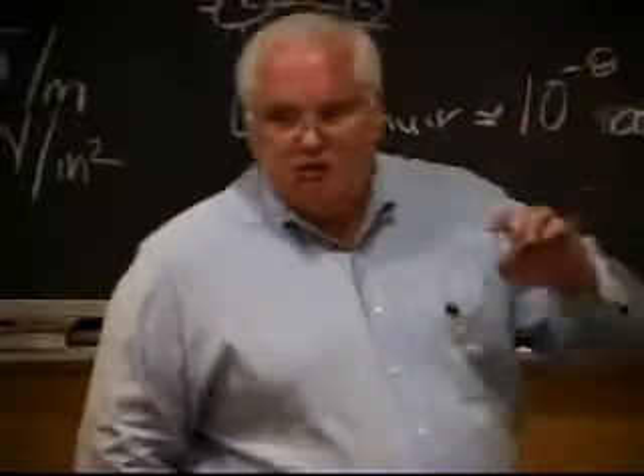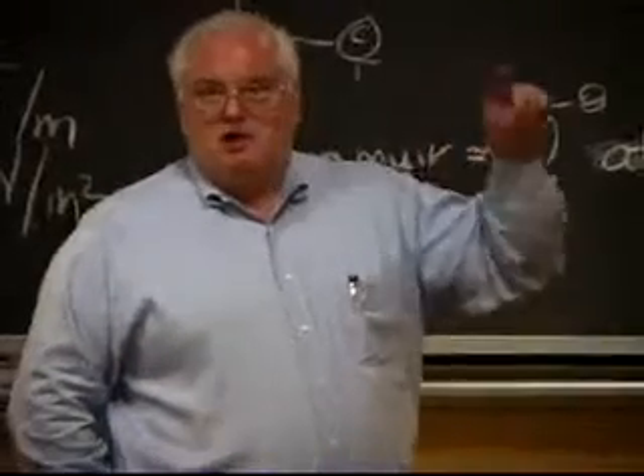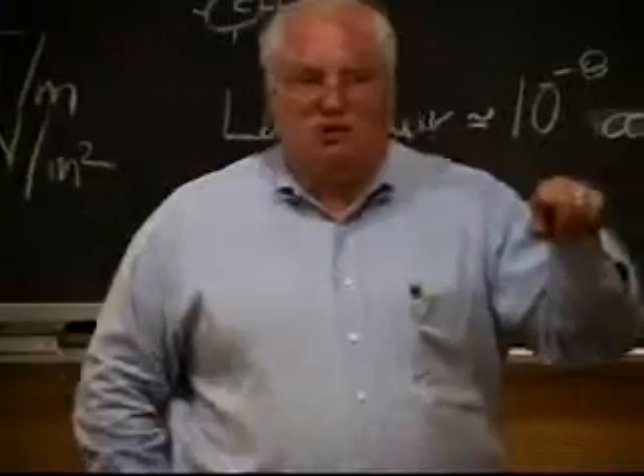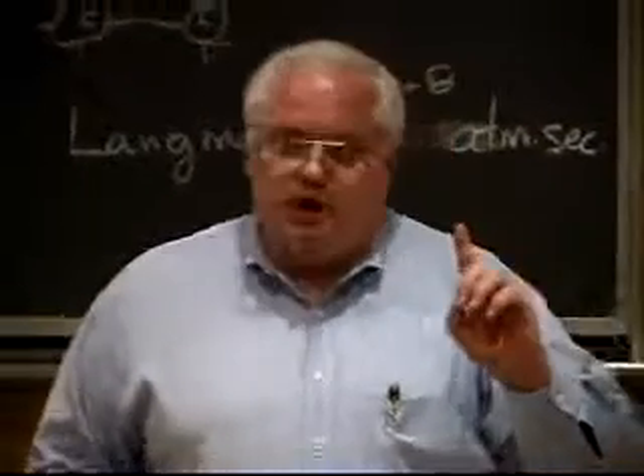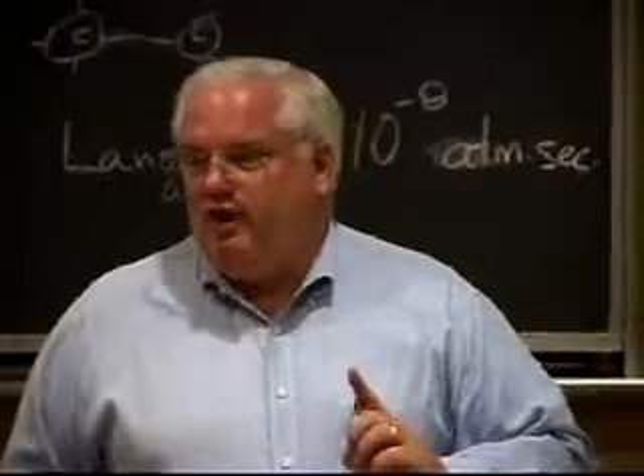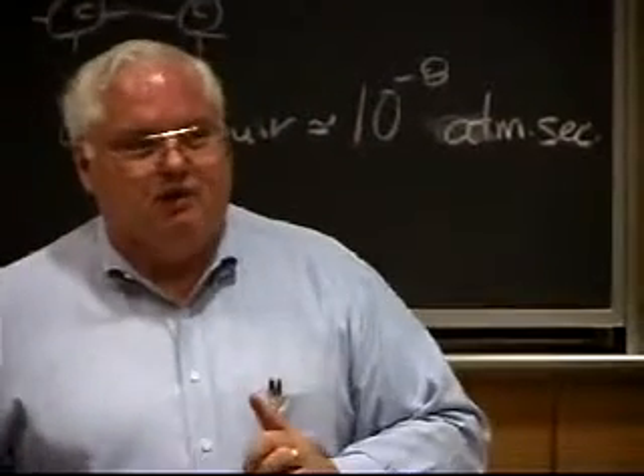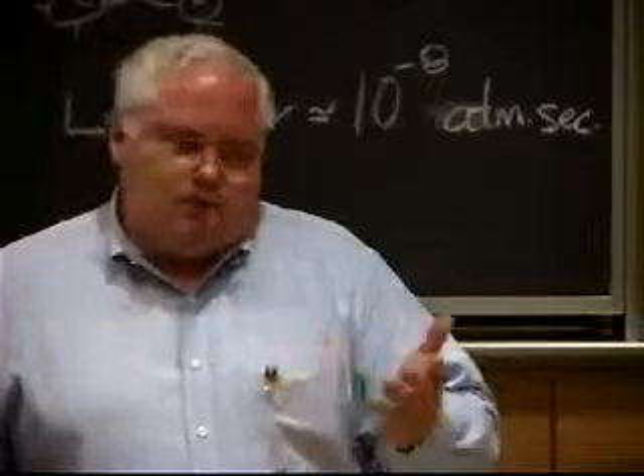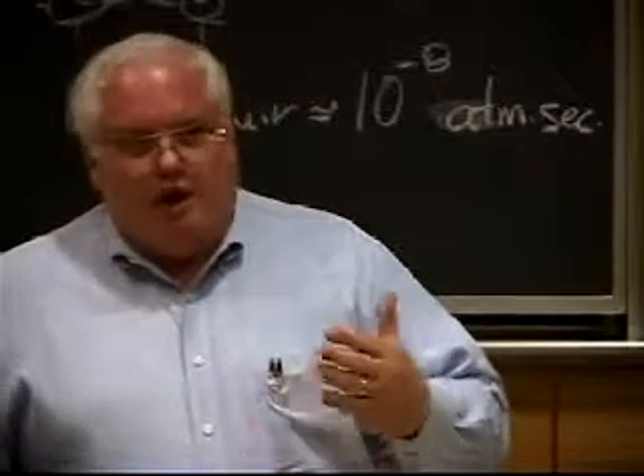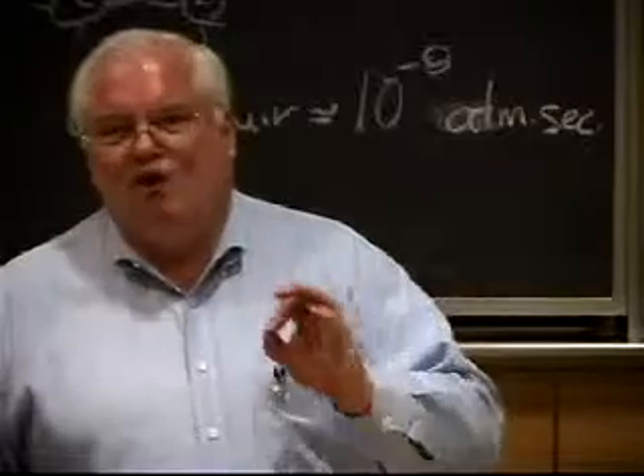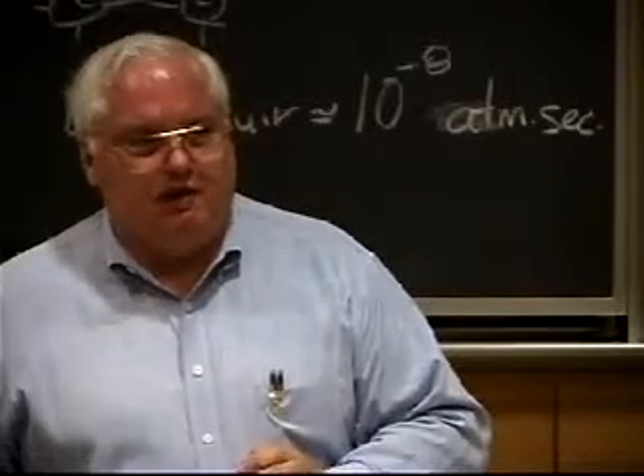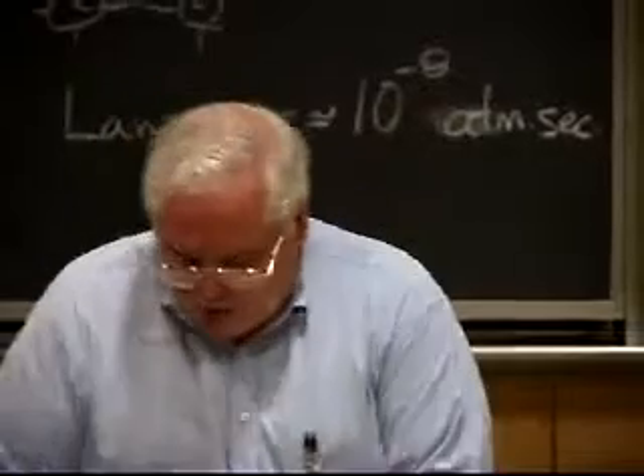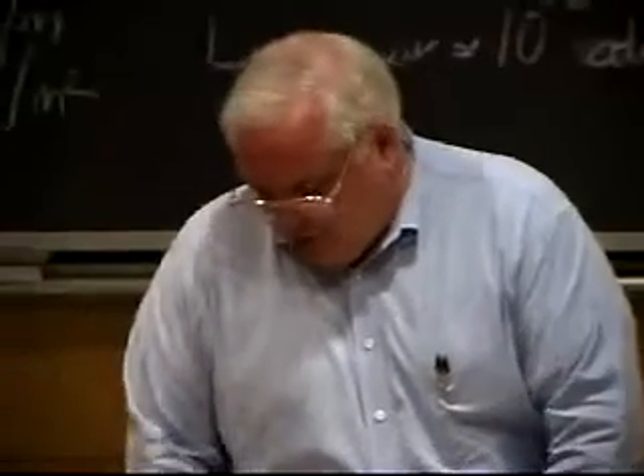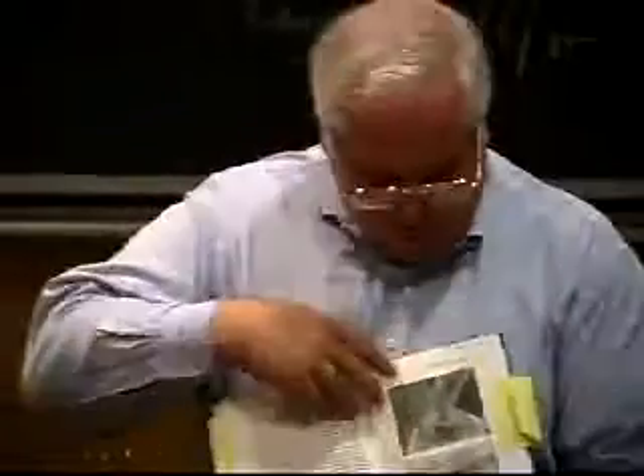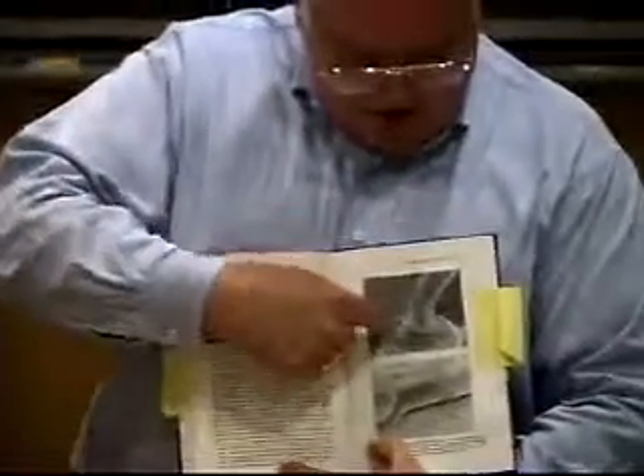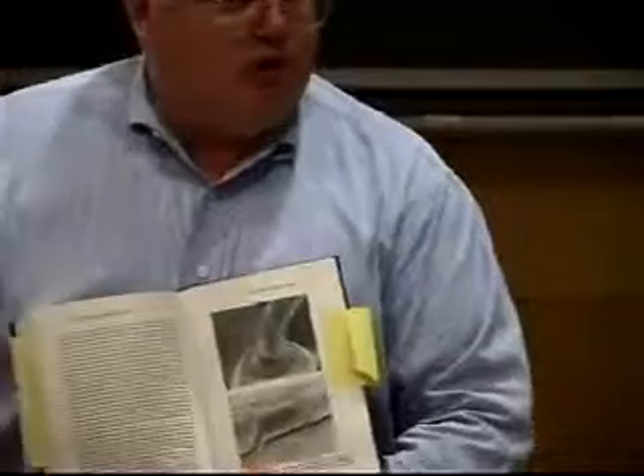Because in the semiconductor packages, when I passed around the little semiconductor chips, there's 360 gold wires making a contact to each one of those. They're gold wires that are only 1 mil in diameter. 1 mil being about 1/3 of a human hair diameter, 1/10 the cross section of a human hair. 1/1000th of an inch. Human hair, depends on whether you got thick hair or thin hair, but it's on the order of 60 to 80 microns in diameter. These gold wires are about 20 to 25 microns in diameter. Very fine, and it's basically called thermocompression. Well, actually, they often apply a little bit of heat, but they're gold wires. And here's a picture of one. Here's the gold wire, and it basically just squeezes into the surface until it mushrooms on the bottom.